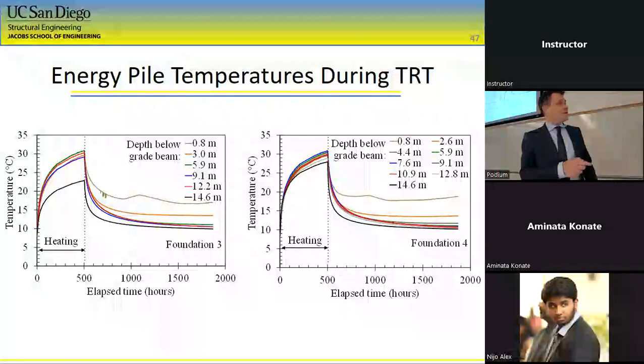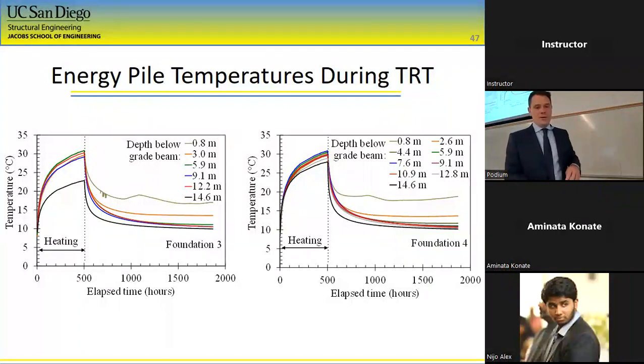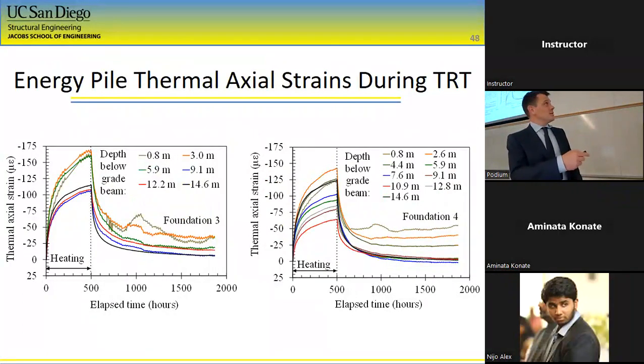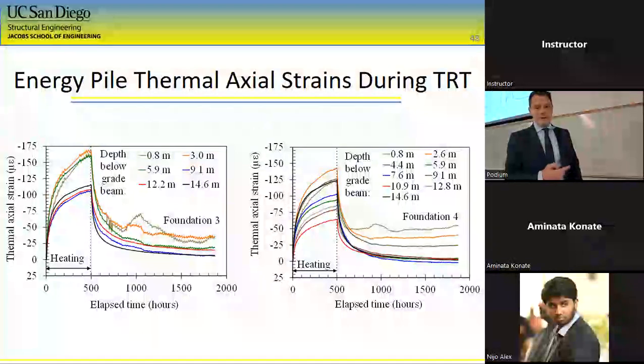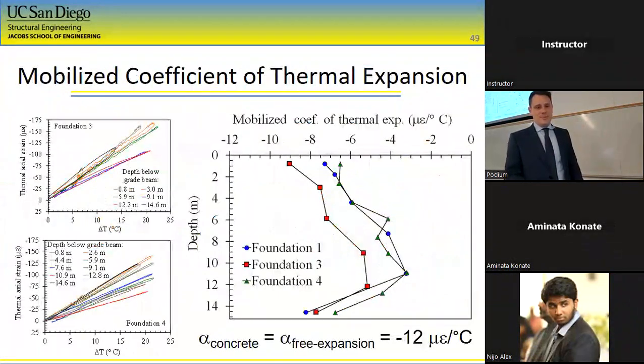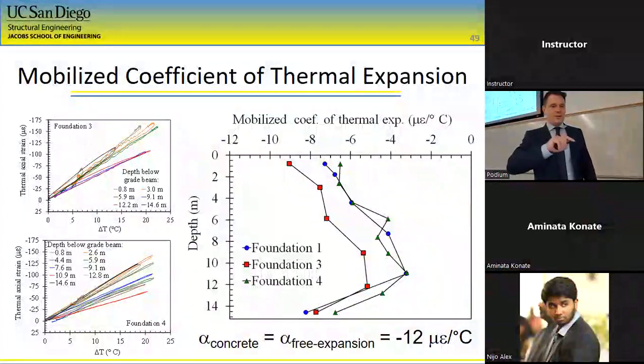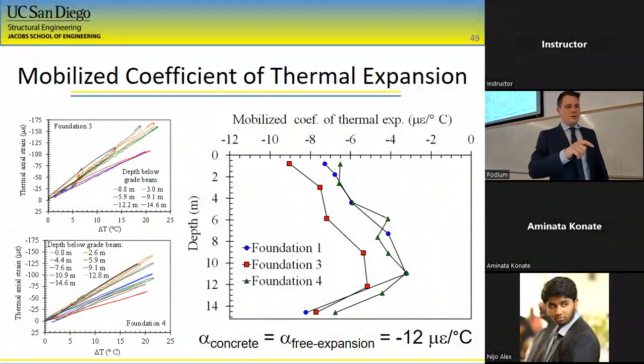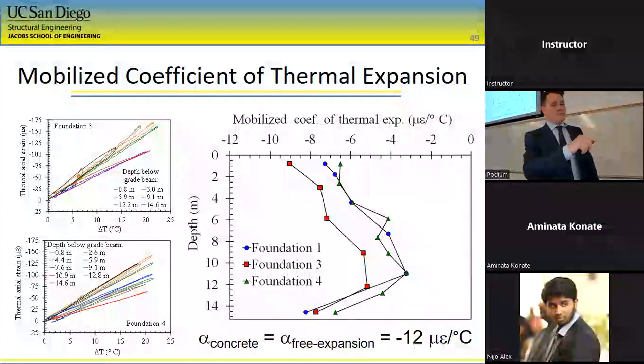So these all, except for this one temperature sensor at the base, the temperature is relatively uniform across the length of the pile, but the strains across the length of the pile were very different. And this is due to the thermal restraint as a function of depth. If we look at each of the strain gauges and look at their temperature versus strain, you can get the mobilized coefficient of thermal expansion, and that gives you a shape like this.